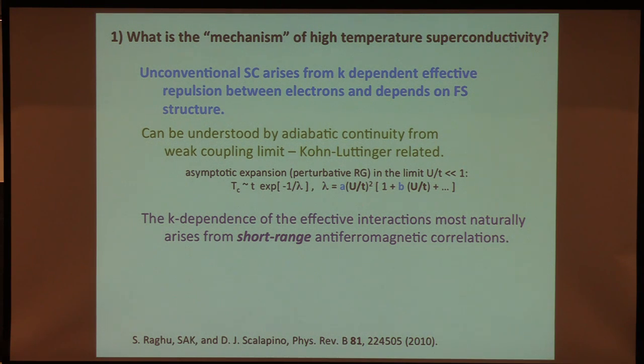And then the second step is to notice that if you have somehow short-range magnetic correlations, that's some statement about the particle-hole susceptibility, which in turn is some statement about the screened effective interaction. So if you want to get an effective interaction that's peaked at some large wave vector, the most obvious and the most well understood way to do that is by being close to a magnetic state, so there's some form of short-range antiferromagnetic correlations.